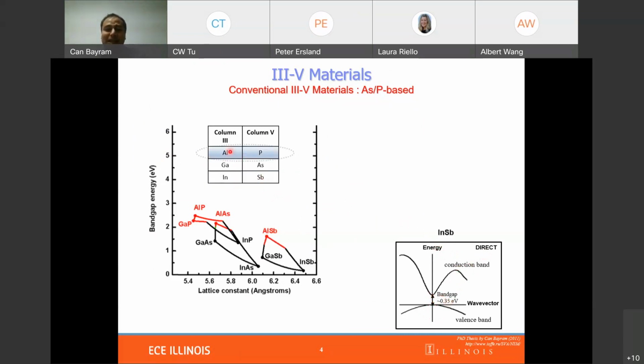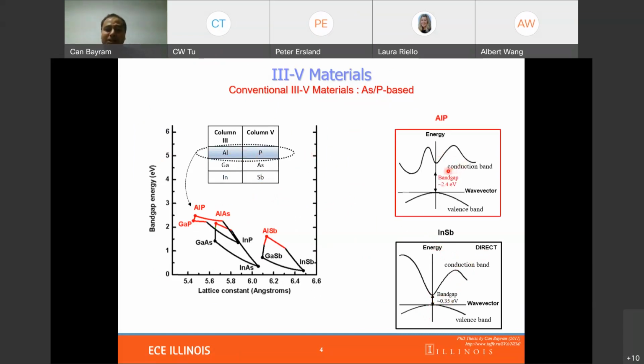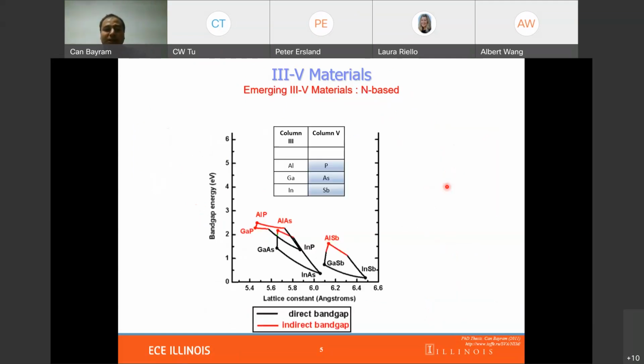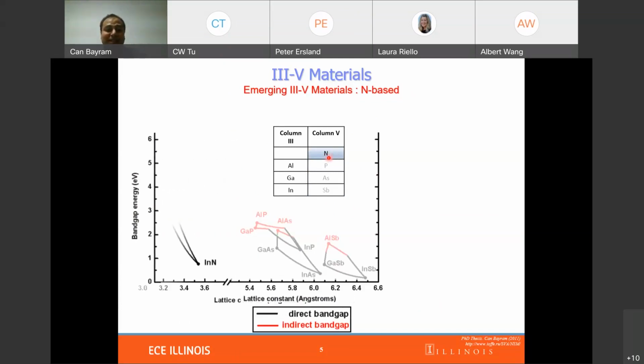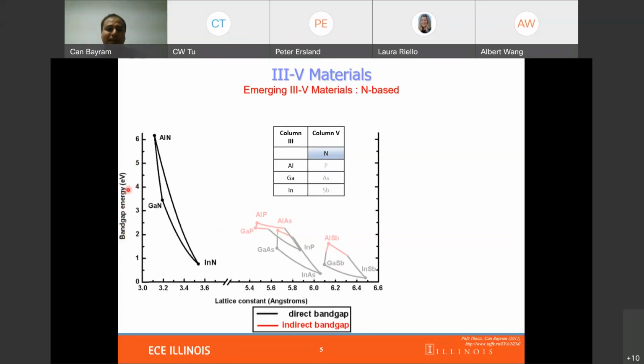Now, if we mix aluminum and phosphorus, we get aluminum phosphide. And when we look at the band structure, we see that it has a wider band gap, but this material is indirect band gap. Now, what we do in my group is we introduce a new element, from column 5, nitrogen, so that we can expand these band gap energies.